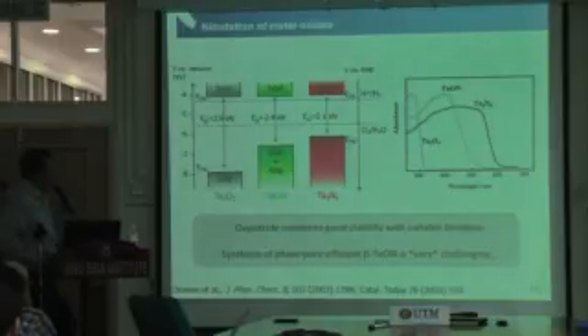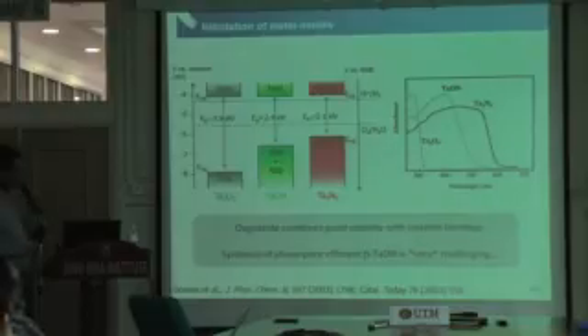And then if you combine them together, combine the oxygen and nitrogen, you get a valence band consisting of hybridized oxygen and nitrogen 2p orbitals, and it's somewhere in between. So it's kind of combining the best of both worlds. The tantalum nitride is good, but it's not stable. Oxide is very stable, but the band gap is too large. And with oxynitride, we hope to combine good stability. But the problem with oxynitride, especially the tantalum oxynitride, is that it's very hard to actually get the phase-pure efficient beta tantalum oxynitride.